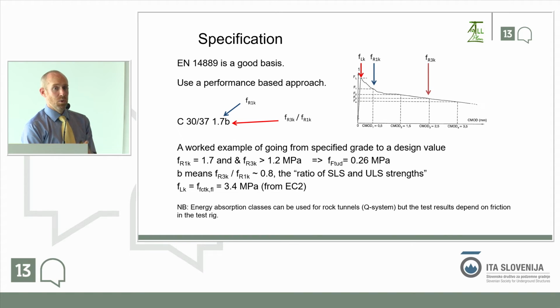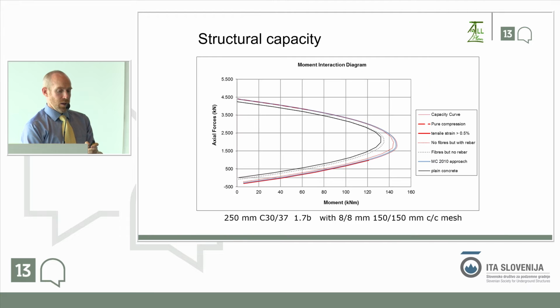You can see from the equation here that the tensile strength you're allowed to use in design by these codes is actually very small. So the consequence of adding the fibers when you look at your capacity curve is very small. And in that sense, as I say, you're sort of guaranteeing a ductility, but you're not really adding a bending capacity. So perhaps the simplest thing to look at here is the black curve.